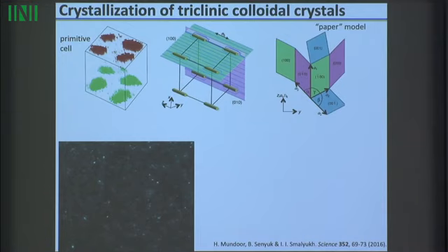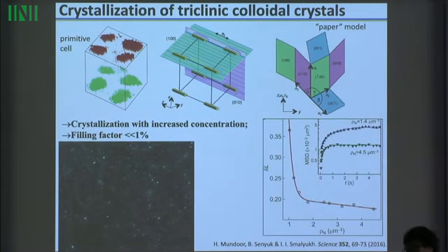And so with just right control, you put nanoparticles and you see them crystallizing in liquid crystal into the lowest symmetry possible, triclinic colloidal crystals, as for example in this our work in the past. And moreover, again, like in atomic and molecular systems, you can reproduce these behaviors of melting and crystallization by, for example, probing the Lindemann parameter.